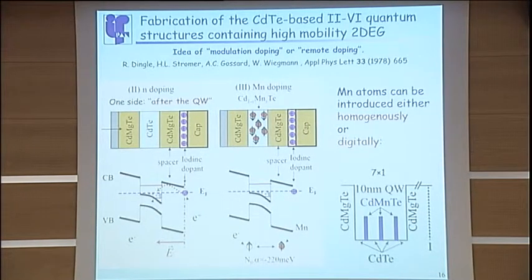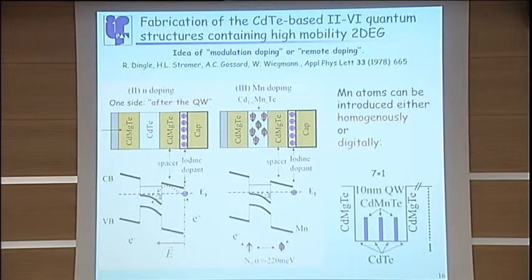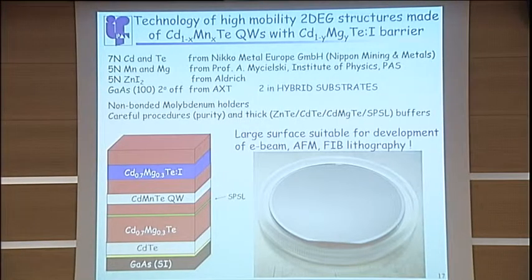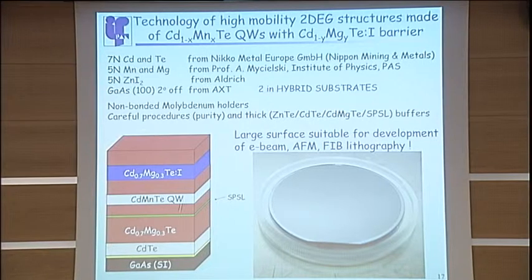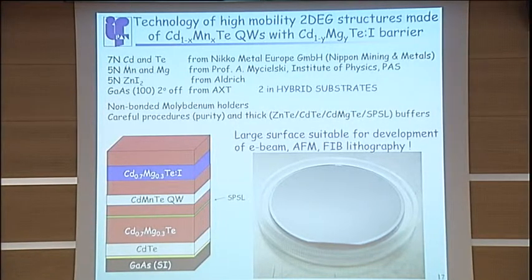And now, in order to introduce manganese, you can do it either homogeneously or digitally. Digitally means that you just put some monolayers of cadmium manganese telluride into the quantum well region. And of course, to get high mobility, you have to be careful about the purity. So you have to choose the best available materials. Also, please note that we use manganese and magnesium, which are produced in our institute by Professor Michalski's group. And we grow our structures on 2-inch wafers. We do it because not only are they inexpensive, flat and high quality, but also, as I said, we want to develop E-beam and other forms of lithography.